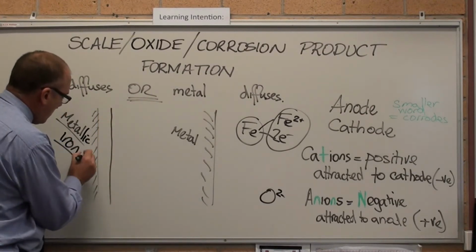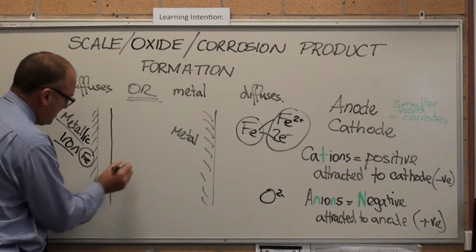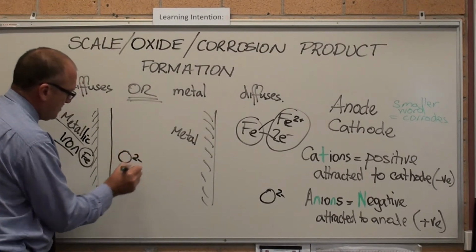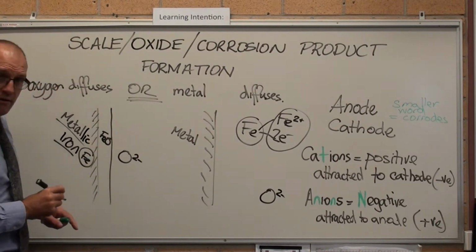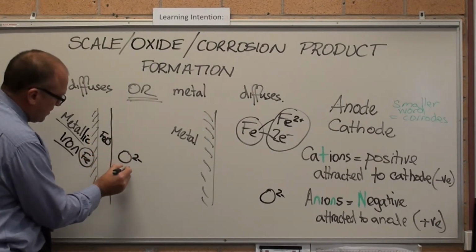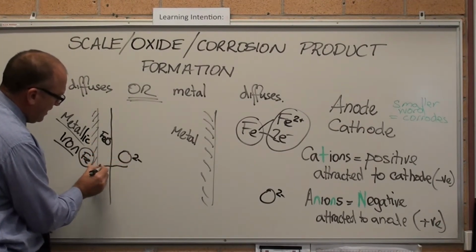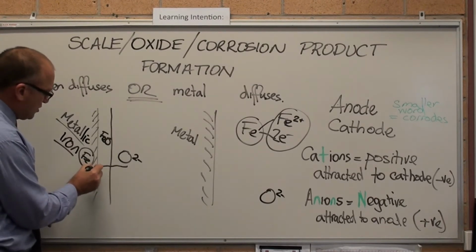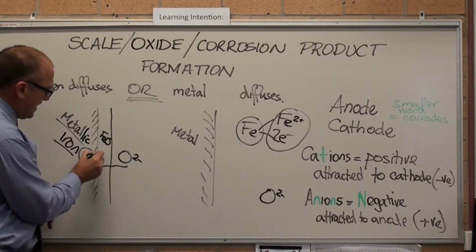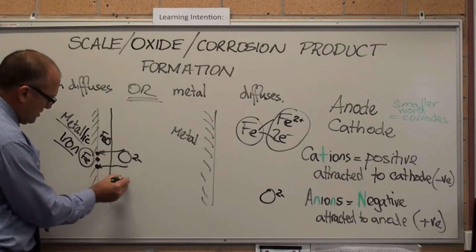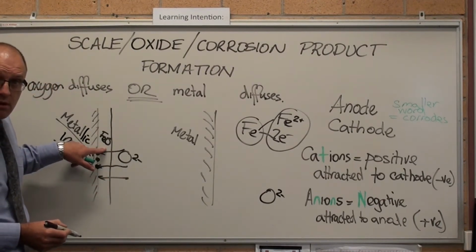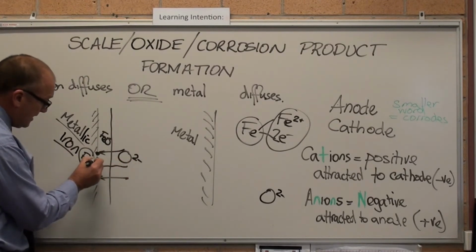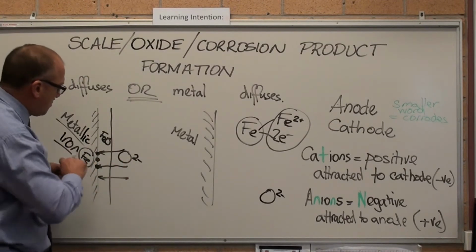So we've got iron here. Here we've got oxygen. And in here we've got iron oxide forming. The oxygen diffuses through here, and the reaction's actually taking place at that interface. Iron oxide is a ceramic, which is brittle. The reaction's occurring underneath, which means it's swelling it out.